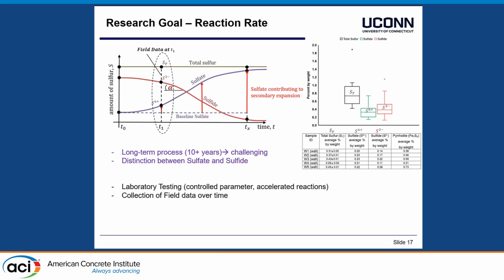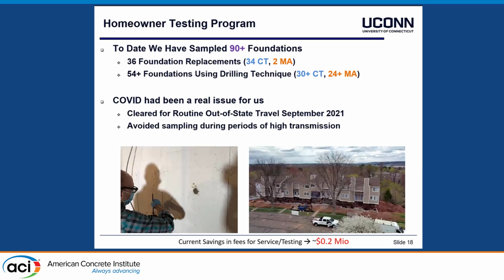an accurate prediction. So in the laboratory test, as I said, we can control all the parameters and also have certain steps included to accelerate those reactions, and the collection of field data over time is needed to develop the database. So far, we have 90 plus foundations being tested. This includes foundation replacements. It also includes foundations like the walls from homeowners, where we used a vacuum drill to obtain the material. COVID had an issue because for a period of time, we couldn't move or schedule an appointment with the homeowners, but now it's getting better.